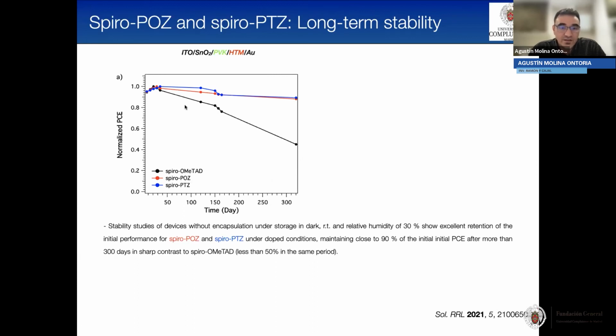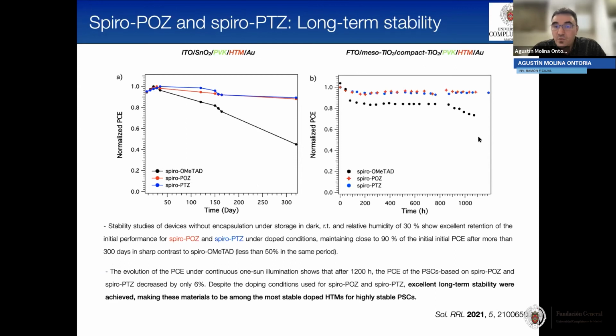And in here, you can see that our hole transporting materials are displaying better stability than those of Spiro-OMeTAD. And this is remarkable because they were stable for at least more than 300 days. It's almost a year.